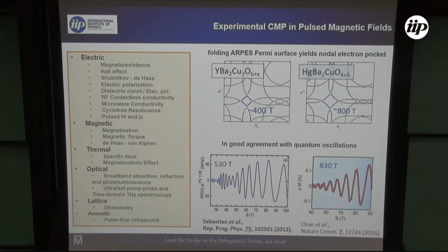So what is the point here? The point is very simple. You have an electron that is moving in a magnetic field, and because of the magnetic field, it turns in an orbit. However, the material has impurities. If the electron suffers scattering on its trajectory while closing the orbit, then you don't see the quantum oscillations. They get scrambled and scattered around, and you don't see anything. In order to have an orbit that is smaller than the distance between impurities, you need to apply a very large magnetic field. The orbits get smaller and smaller and smaller.